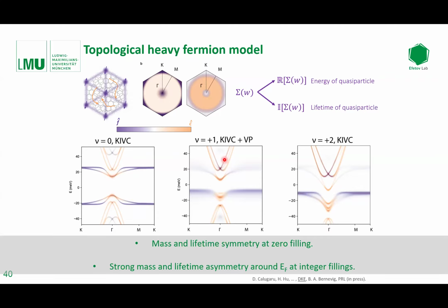Whereas if you look at the different ground states at filling factor 1 and filling factor 2, all of them are electron-hole asymmetric. So if you excite on the electron side, you will always be dominated by these dispersive C electron bands, which have a long lifetime and dominate the transport. And if you go to these hole excitations, you will see that really flat bands with a very low lifetime and a very reduced transport coefficient would give you the transport signatures.